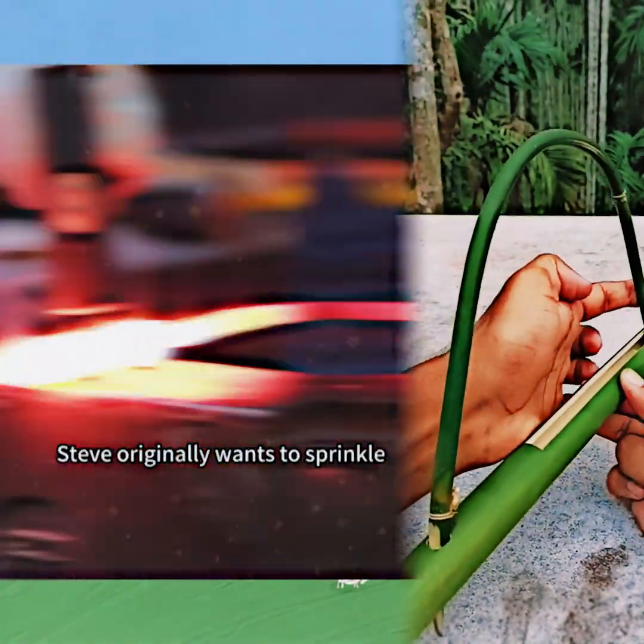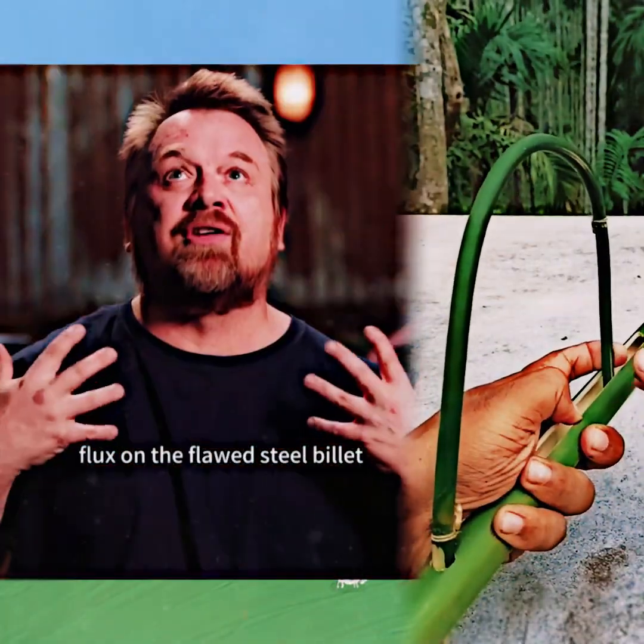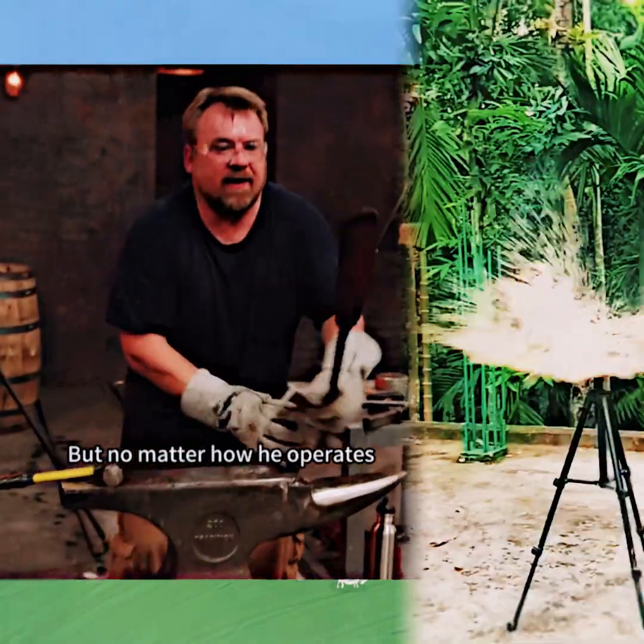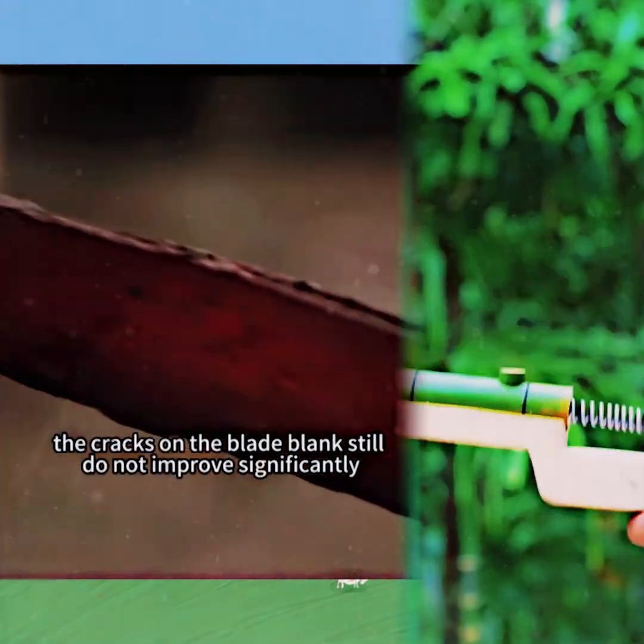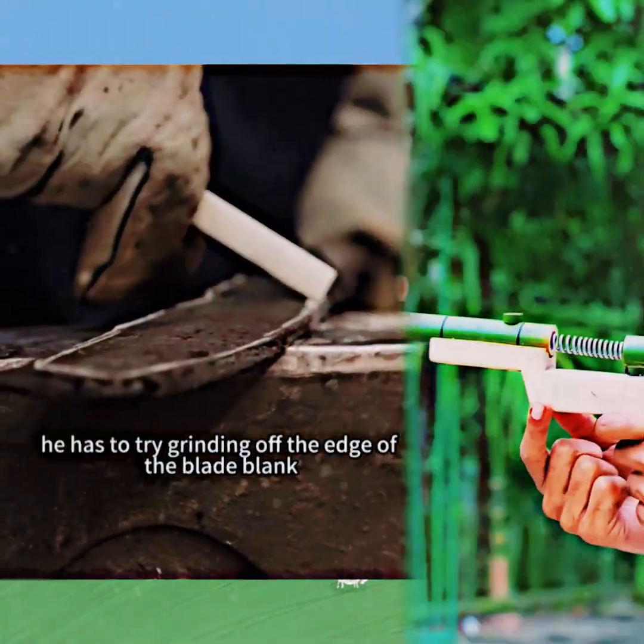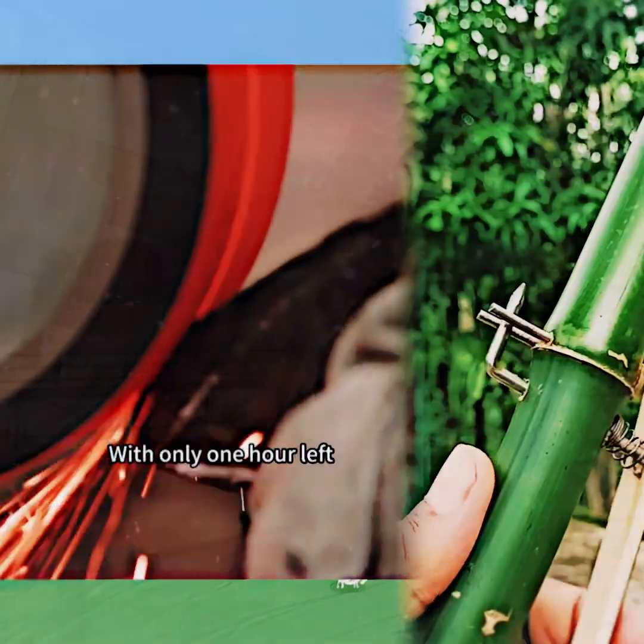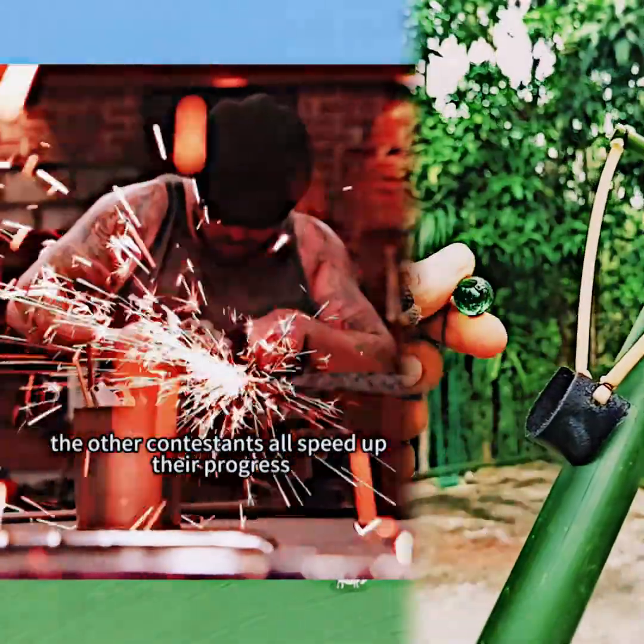On the other side, Steve originally wants to sprinkle flux on the flawed steel billet and hammer it again. But no matter how he operates, the cracks on the blade blank still do not improve significantly. In desperation, he has to try grinding off the edge of the blade blank. With only 1 hour left, the other contestants all speed up their progress.